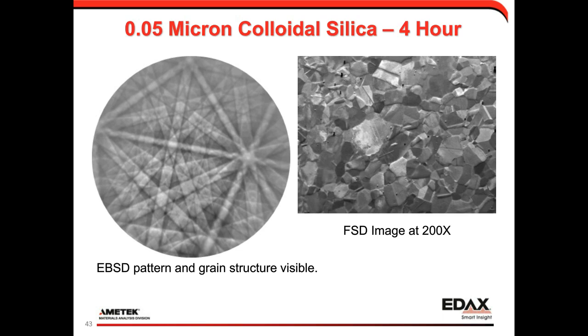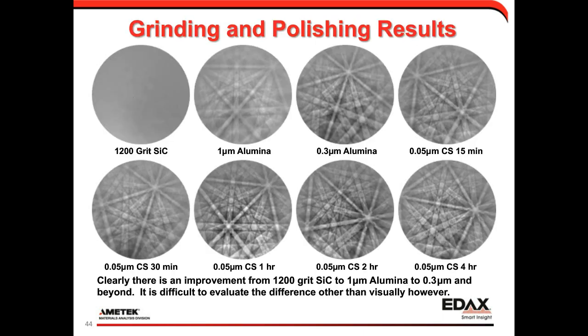And so it's one thing to kind of see them one after the other. But if we put all the patterns together on a single slide, it's easy to see the improvement from 1200 grit to 1 micron. And I think it's relatively easy to see the difference from 1 micron to 0.3 micron alumina. Beyond that, it can be pretty difficult to tell by eye, and that's why I talked about paintings and subjective evaluation to start. Because what we want to be able to do is go beyond a subjective evaluation. We want to use some of our metrics to actually quantifiably determine how good a diffraction pattern is.